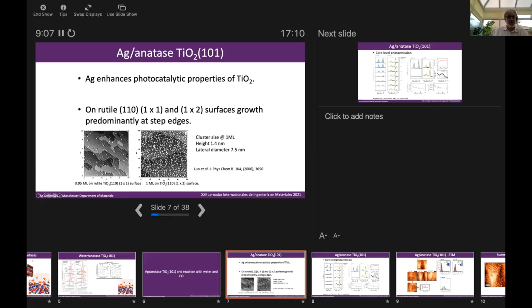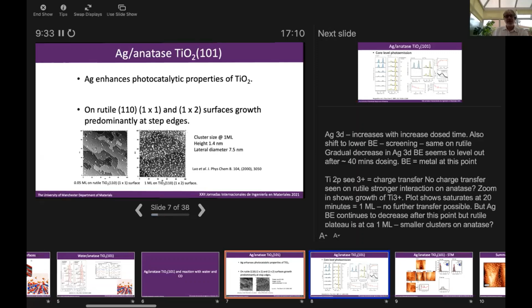And we also saw that we did get some clusters forming on the terraces, but the majority of clusters tended to form along the step edges. And this is due to the fact that silver has quite a low interaction with the rutile surface, so the atoms skate across the surface until they hit a step edge, and then they can't get up the step edge, and there are defect sites for it to attach to, and then subsequent silver atoms build on these clusters as well. So we wanted to see what happens on anatase.